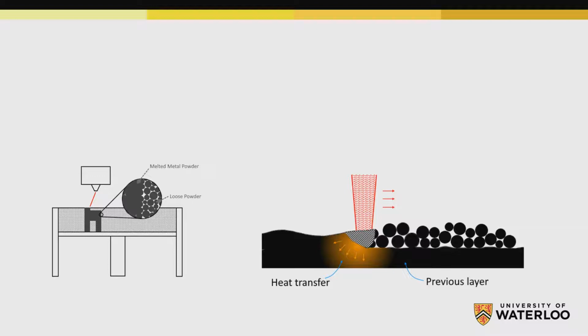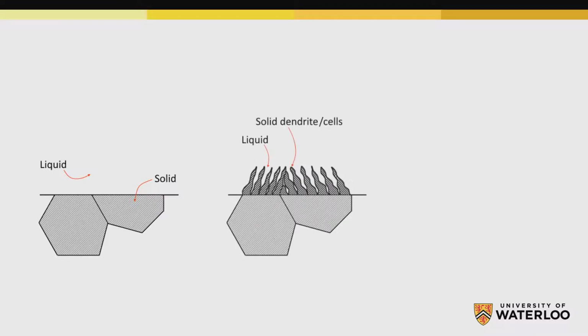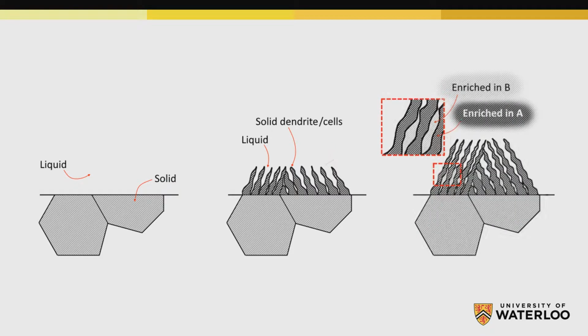During this process, a melted alloy cools within a temperature gradient, and directional solidification occurs. The result is the formation of small cells or dendrites originating at the solid-liquid interface. The size of these cells is controlled by both the temperature gradient and the solidification front velocity. Due to differences in solubility, the boundaries of the cells are often enriched in some elements and depleted in others when compared to a properly homogeneous alloy.